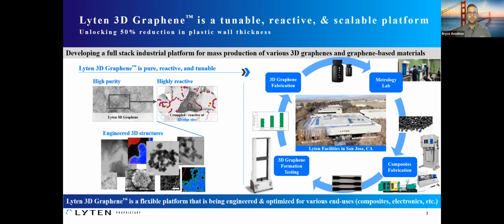And really what the 3D graphene enables that a 2D material doesn't. If you look at a 2D material, you typically rely on just the edges. So maybe 1-2% of that full material surface area is allowed to react with a medium, for example, plastic. But if you're able to modify and architect that to have more edge sites or more reactivity on areas that were traditionally a basal plane without reactivity, then you can get higher reactive sites, and you have a better interfacial bond between the graphene and the host polymer, for example. So that's one main difference.